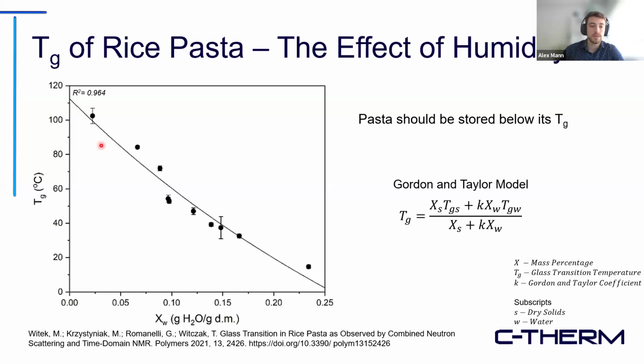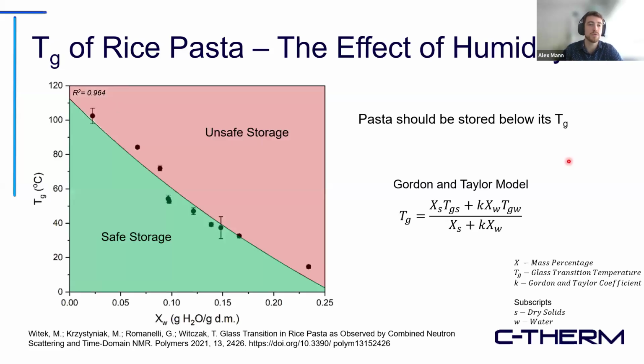As we can see here, with an R squared of 0.964, the data fits the model prediction pretty well. We see we have the nice slightly curved line as the model prediction, and then the data points are what was sampled. So this is important because pasta needs to be stored below its glass transition temperature.